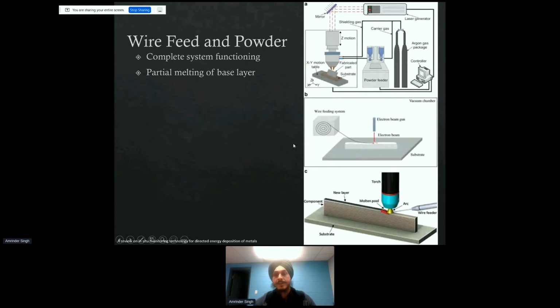Now, before we go ahead, let's touch base on the complete system functioning. So we have to have a controller which can control our movements, a powder feeder which can feed the powder to our coaxial nozzle, and the argon gas. As we are cladding or doing additive manufacturing of parts, we have to make sure that the melt pool does not come in contact with the atmosphere. For example, iron-based alloys can get oxidized very easily, and then we can have defects in our final product. So that acts as a shielding gas.